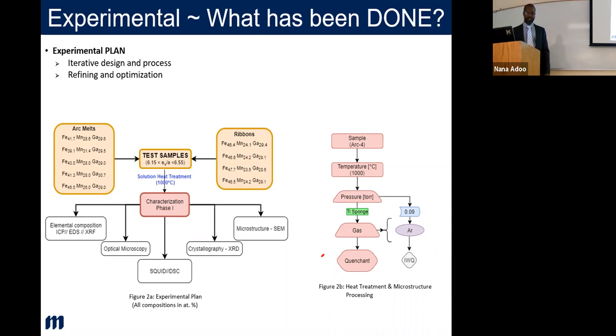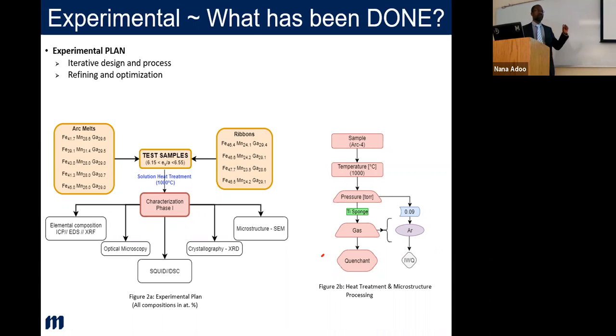The titanium sponge being used here is actually a control which will ensure that there is no oxygen in your system, and to ensure that those materials are bound to transform once you are done with the treatment. So without delaying in these processes, I actually try to minimize the time frame between the heat treatment and then the quenching process.